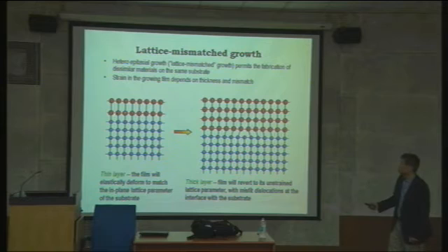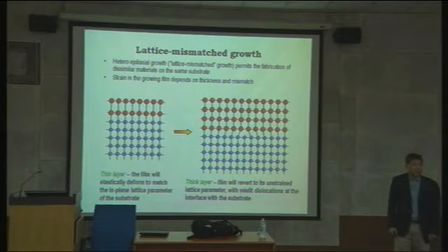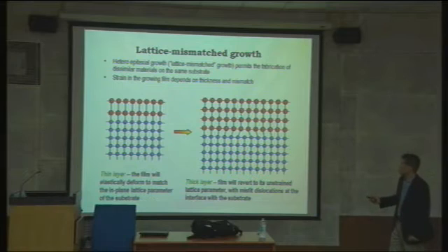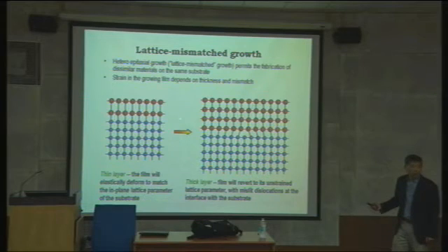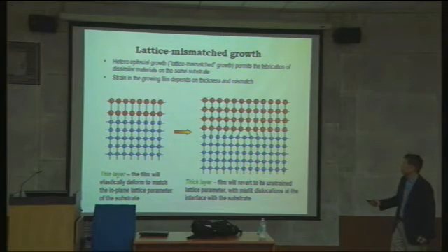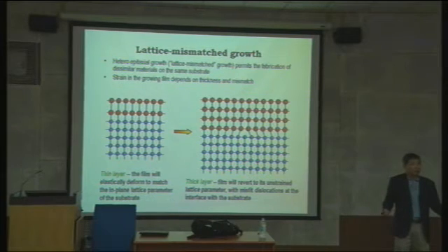If the in-plane lattice parameters of those two are exactly the same, that means coherent. And the out-of-plane lattice parameter, when you measure it, looks bigger than bulk because you have actually stretched it. In a completely relaxed case, the in-plane lattice parameter is the same as bulk. But sometimes it's not completely relaxed, it's partially relaxed. So the value is not really like bulk, but somewhere in between.